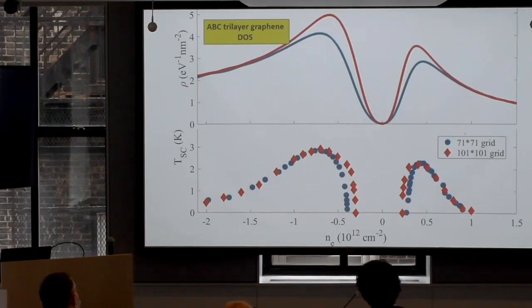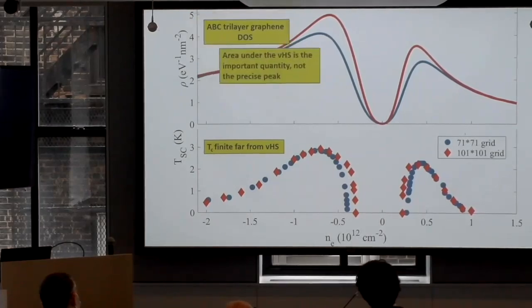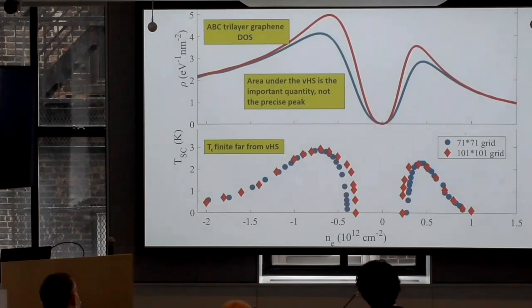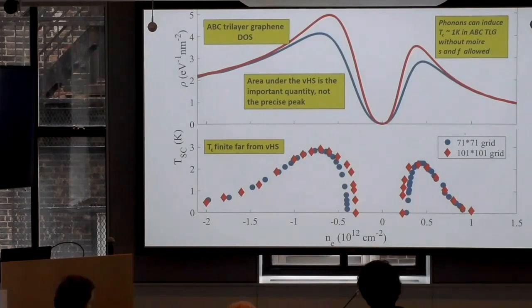This is electron-phonon, and the important thing here is to what extent it agrees with experiment. Experimentally, he finds 1.5 roughly. And we argued here that maybe mu star effect reduces it slightly, but it's reasonable. So you can get Tc of 1 K in ABC trilayer graphene without moire, and both S and F are allowed.